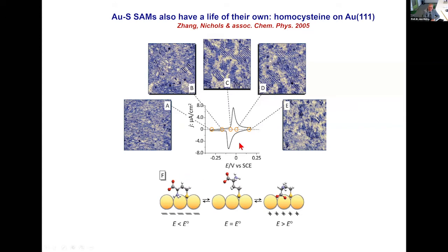We can see, for example, if we follow a voltammetric scan, when we are far away from the peak, there is largely disorder over the whole surface. Then as we approach the peak potential, we can see that the molecules begin to assemble and form broad areas of highly ordered domains. And they disappear again when you get to the other side of the voltammetric peak. In other words, we see a kind of phase transition. And that means with a phase transition, electrons run to or fro the surface, and the instrument registers that as a current. But it is not a Faraday current, it's a capacitive current. So if we see odd signals, we have to have in mind that the self-assembled molecular monolayers can have such a life of their own.